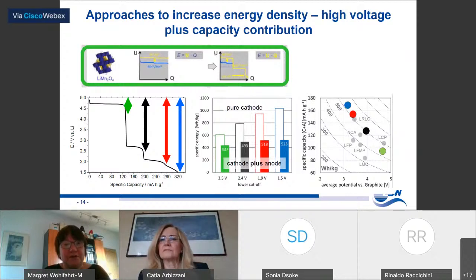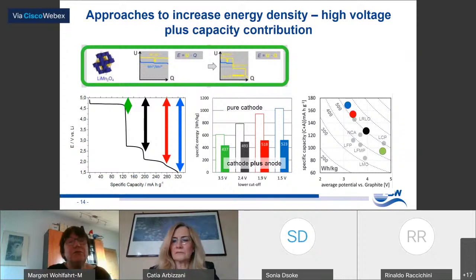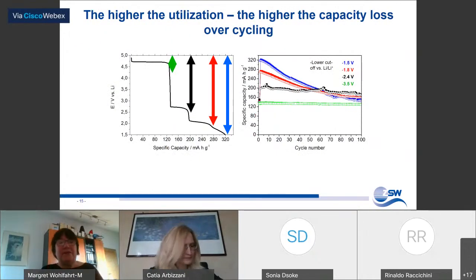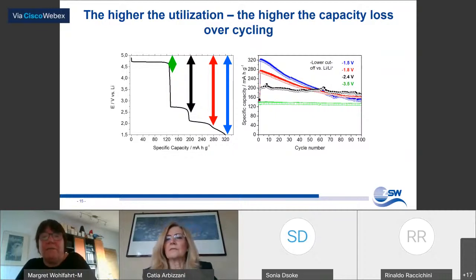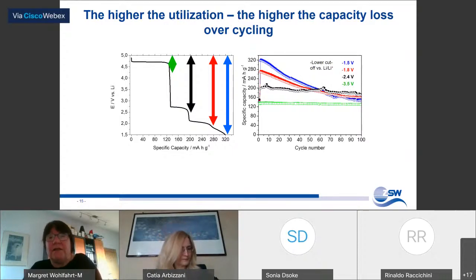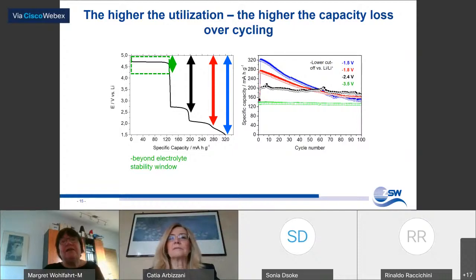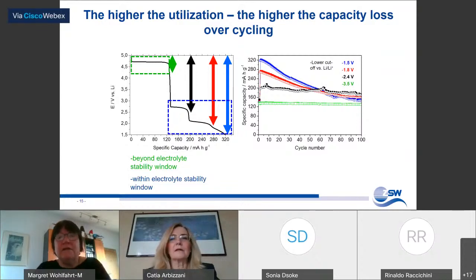We can insert one more lithium inside the structures, which leads to very high specific energy, if it's possible to use this additional capacity. But there's one point: the higher the utilization of the material, the higher the capacity loss over cycling. You can see here, if you cycle only on the 4.7 volt plateau, the material is very stable. If you go to 320 milliampere hour per gram, which is near the theoretical capacity, the cycling stability is quite low.